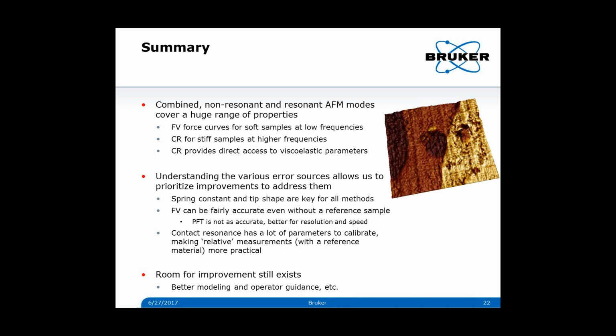Understanding the error sources that are going into these measurements really allows us to prioritize improvements to address them. So this time around, spring constant and tip shape were the ones we targeted. They're important for all the methods, and we showed that force volume can be fairly accurate even without a reference sample. Peak force tapping is still pretty good, but not as accurate as force volume. And contact resonance really has a lot of parameters to calibrate. So we typically do those measurements with a reference material, ideally an internal reference.